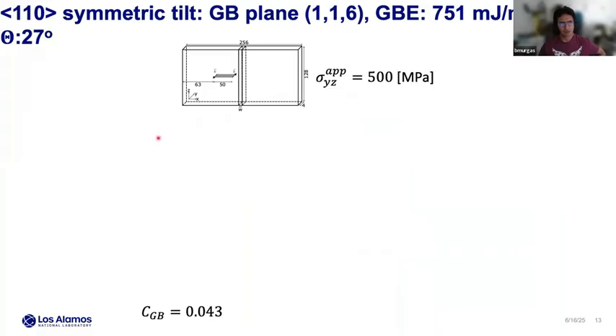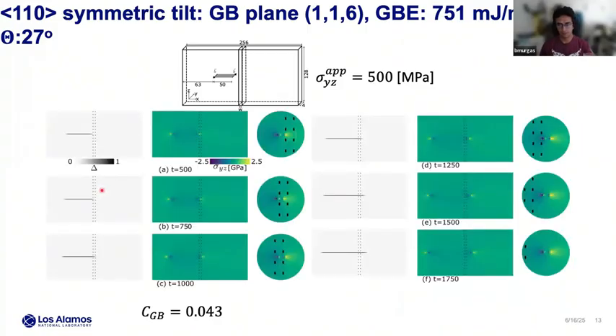So for the first case, we studied this 110 symmetric tilt grain boundary. Sorry, I don't see it well, but we have a different grain boundary plane, with a grain boundary energy of 751. We are applying a shear stress, and you can see that the dislocation starts evolving towards the grain boundary, and sometimes it constricts, or gets compressed, and then after the grain boundary transmits, it just goes back to its original width. This constriction is actually pretty common, we can see it also in MD. Most of the time it gets compressed and then the grain boundary decides where it's going: if it's going to remain pinned, collide towards the grain boundary, or get transmitted. In this case, it just gets transmitted here.